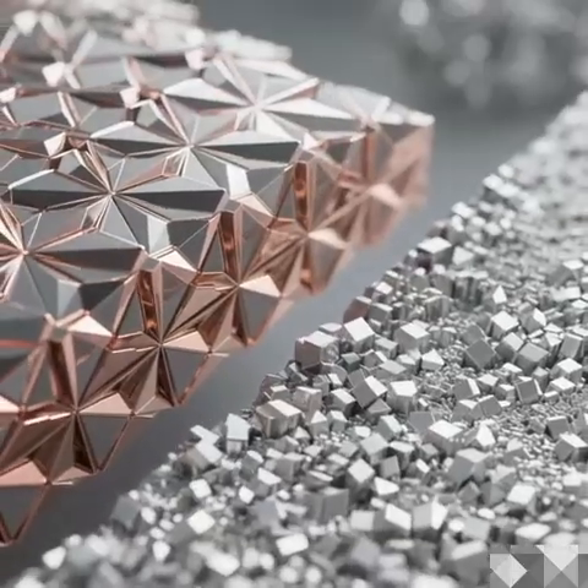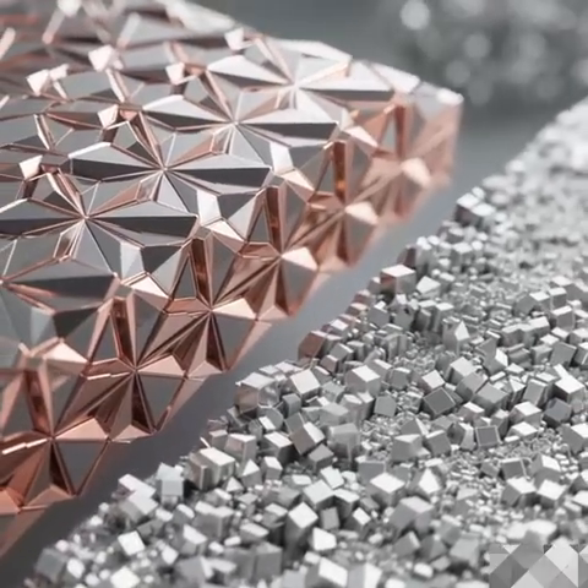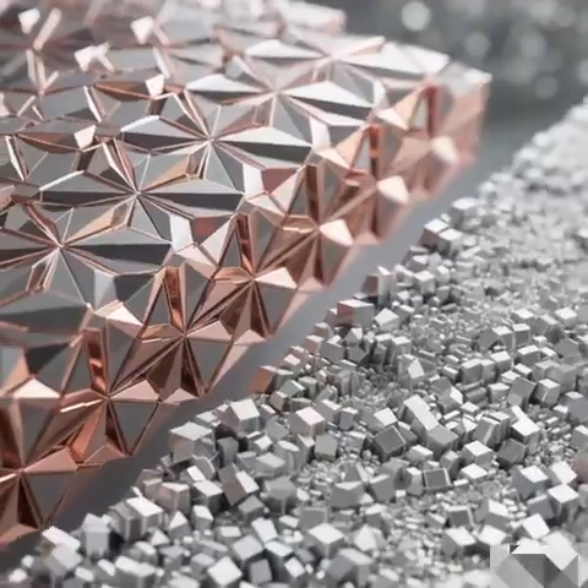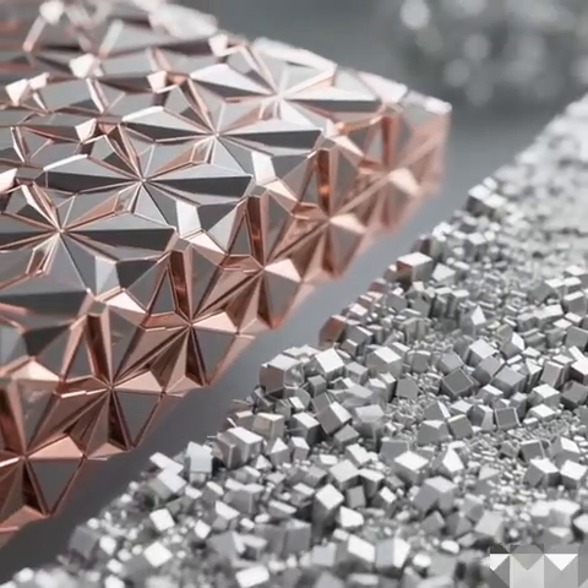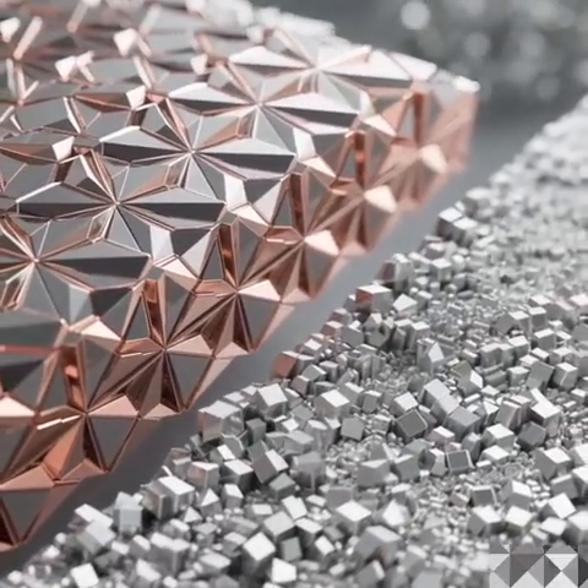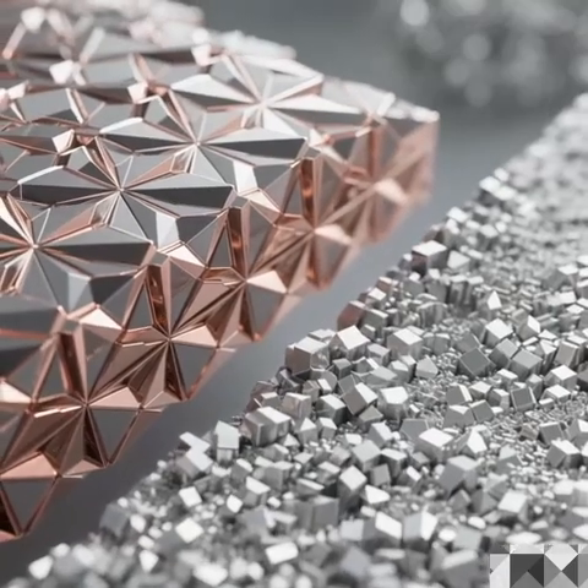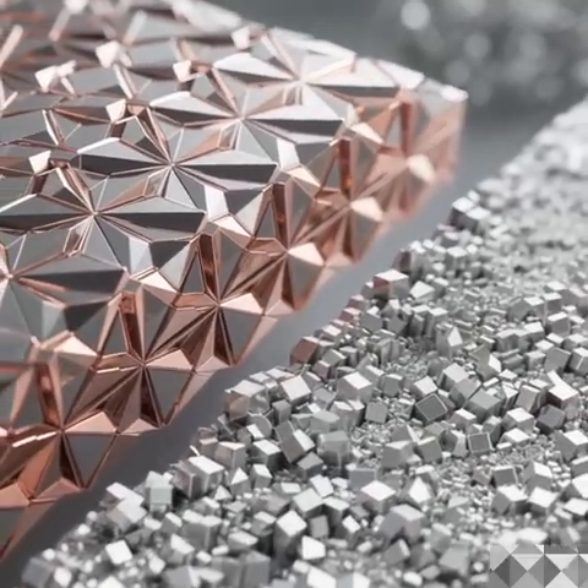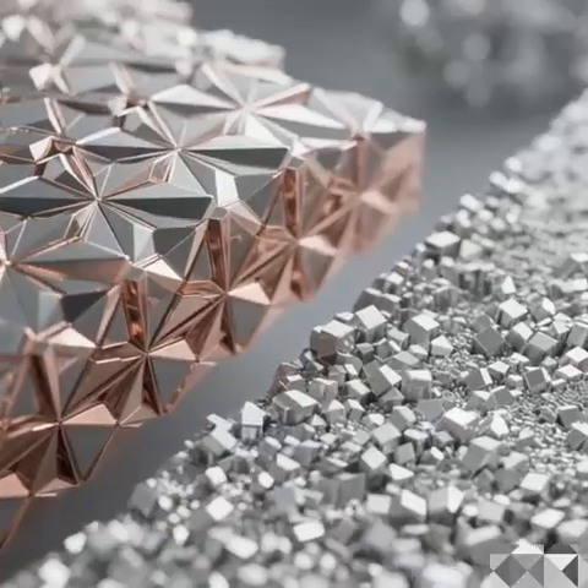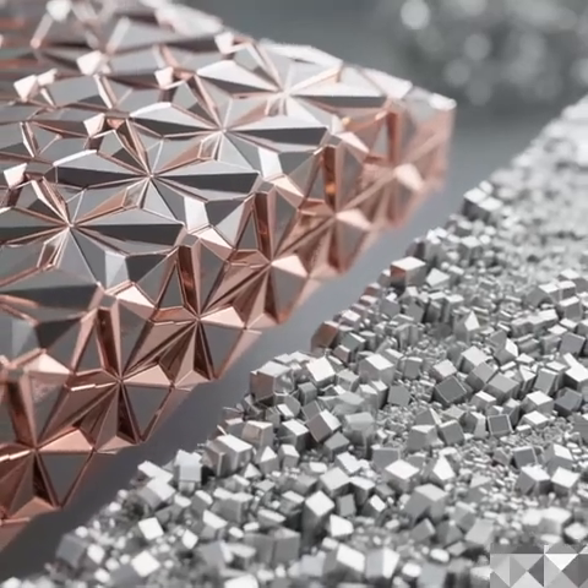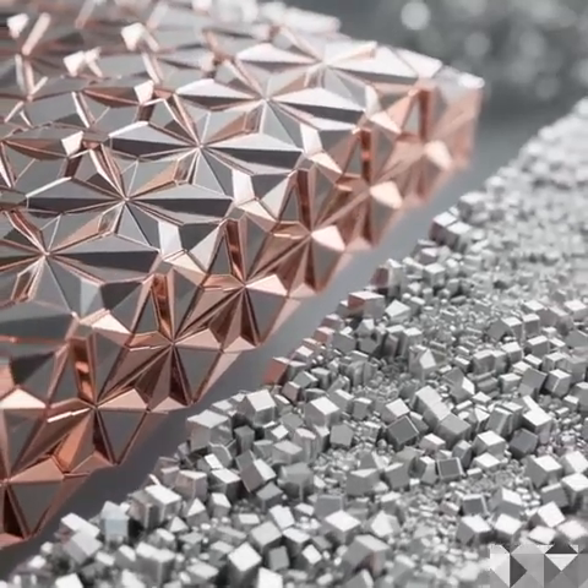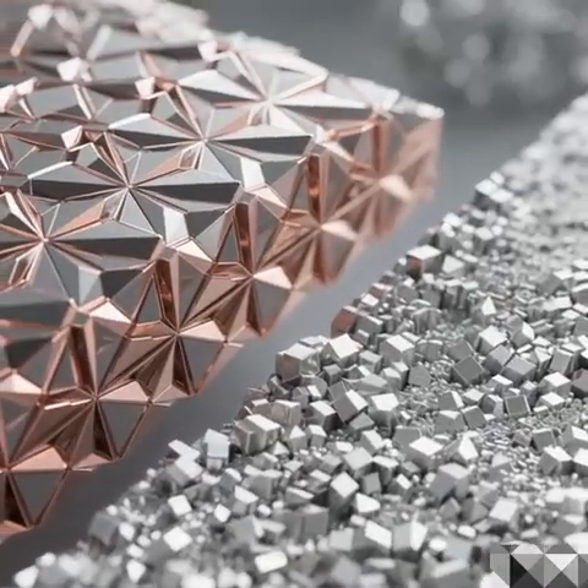Very small grains, yes. And what that means is you have a huge number of grain boundaries packed into a small volume. And those boundaries also act as diffusion paths. They do. But NCC uses this really smart dual-layer strategy. Okay, tell me about that. It's not just the NCC. No, it's a combo. You have a thin top layer, maybe 300 nanometers, of the nanocrystalline copper. Right. But underneath that,